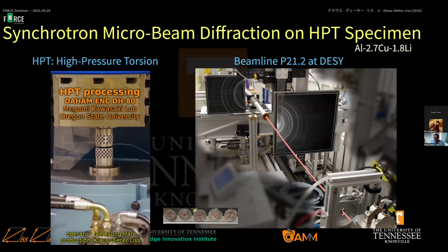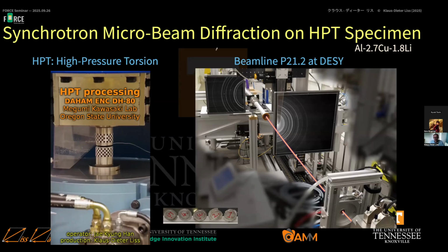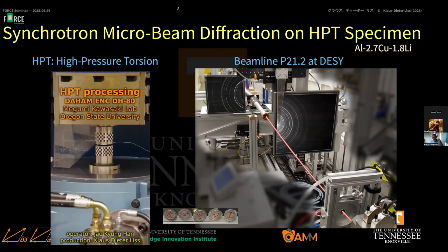So this is the setup. We have here a furnace with a hole in it where the X-rays go in, and we heat the sample, just to show how it looks on the beamline, and that goes further to the beam stop. And then we have detectors here and detectors there. And then as a function of temperature, which we apply in the furnace, we get diffractograms.